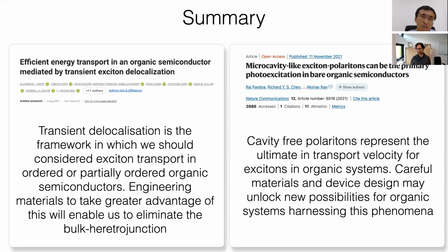Before those excitons can annihilate with each other and have a chance to break bonds in the system. So in fact, if you have a very high efficiency organic photovoltaic device, it should be very stable, right? Because you're using all that photon energy very efficiently. You're not wasting it. You're not using it to break bonds or create heat in the system. You're using it to generate charges. So the efficiency in OPV should correlate quite well with the photostability in the end, if we have good materials.